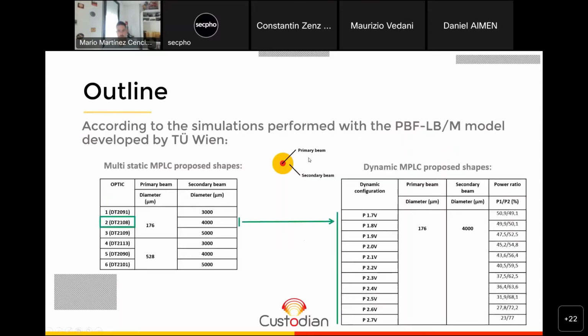So, as shown in previous presentations, based on the outcome of the simulations carried out by the Technical University of Vienna, we started working with a multi-static MPLC, multi-static beam shaper. This means that we have up to 6 different optics, as you can see in the table on the left side of the screen, that could be substituted in situ to modify the shape. So, as we can see on the table, different primary beams are combined with different secondary beams with the intention of mapping different cooling rates, different conditions, right?